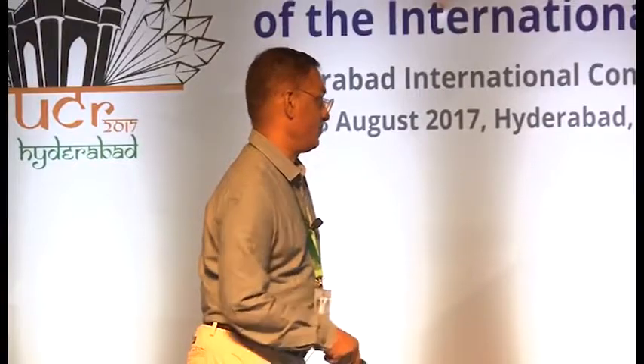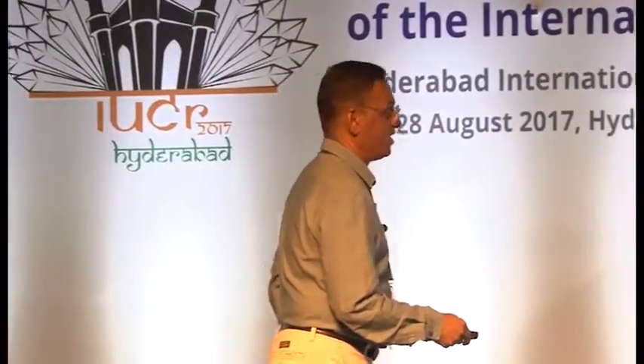So these two we have found to be photoinactive, but this compound, he found to be photoreactive. In fact, there's not much difference between these two. Previously, when we published this paper, we didn't pay much attention to the solvent that is present in the channel because it's highly disordered. We just modeled it as disordered water and we published. We thought, who is going to care about what is present in the channel? So at the time, we published this as water. But you cannot have these two, because this is one MOF with water. When you heat it up, cool it down, it takes back water. This is photoinactive, and this is photoreactive. How do you explain? And the photoreactivity also gave rise to a different type of isotactic polymer.